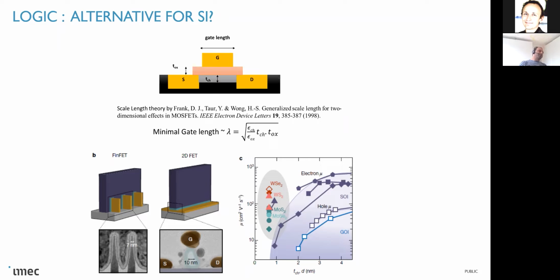The other thing that we need to take into account, of course, if you make the gate length extremely narrow, is that we avoid source to drain tunneling. This is done by going to relatively high effective masses. But the nice thing about 2D materials is that you have a zoo of them, so that you can really choose the one that is the most interesting to have enough high effective mass, but still that thinning behavior.